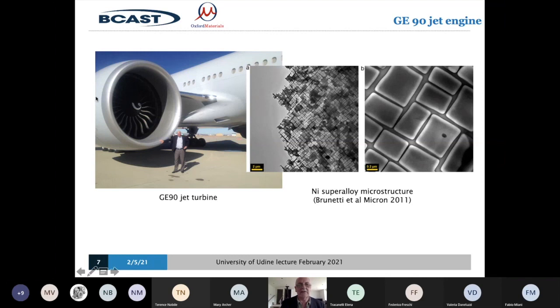And it gets very, very hot in that center where the turbine is. The structure of the nickel alloy, the superalloy it's made from, and by the way, the temperature of the air is about 200 degrees higher than the melting point of the material, which is one of the wonderful technical secrets that we've learned to develop our aero engines. This background here is the nickel, which is relatively soft, and then it's hardened, but it gives it a high temperature strength, and it's hardened with this nickel aluminide here, which is a hard particle, which in a similar way to the steel provides the strength.